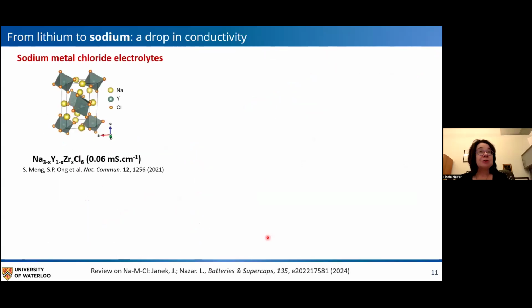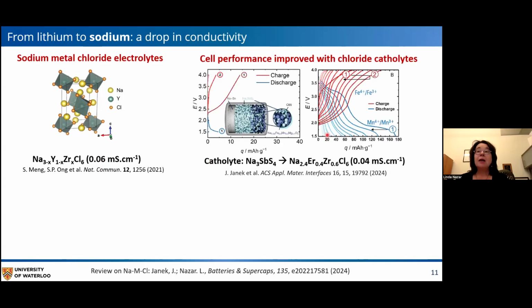So let's switch gears from lithium to sodium. In the case of sodium, there are analogous halide materials. This shows a sodium yttrium zirconium chloride, also reported by Shirley Meng's group. And the sodium materials tend to have much lower conductivity than their lithium analogs. But they still function fairly well in cells.